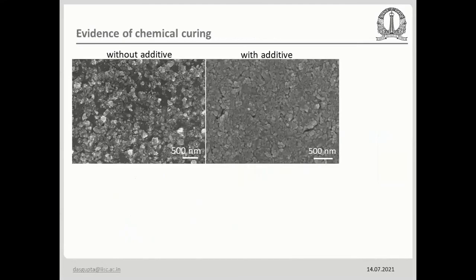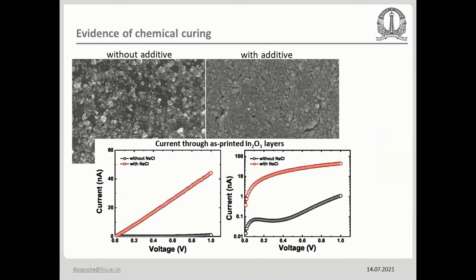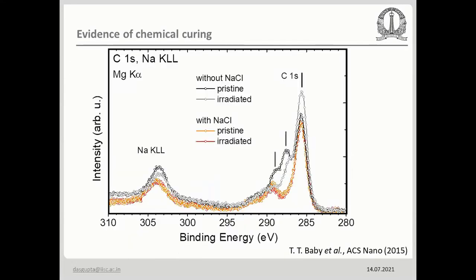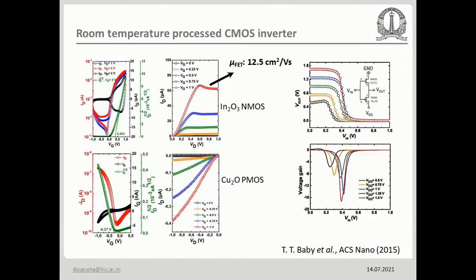So this is without the additive. The left hand view graph, SEM image, right hand view graph is with the additive, and we can right away see a very large change in conductivity. Also with additive, the ligands are gone, high conducting. Without additive, the ligands are there, it doesn't conduct. Okay. And this is also proved by the experimental data, it shows the chemical curing is working, and we have demonstrated fully room temperature printed transistors, P and N type, and some inverters and so on.